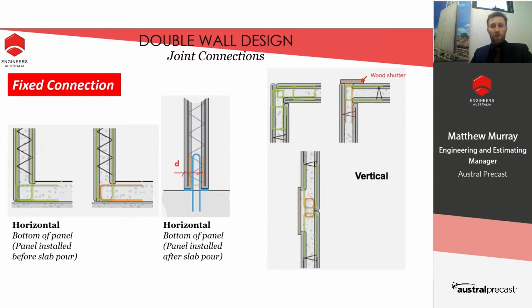What we do with the fixed connection is we provide a U-bar that is cast into the panel and then a stirrup that is placed on site to essentially tie the two shells together. This section requires the one edge of the shell to be shorter than the other to expose the U-bar, which leaves an opening on site for placement of the stirrup, which is then completed with formwork on site.